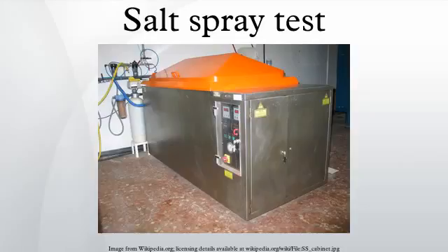The first climate cycle comprises a continuous indirect spray of neutral saltwater or synthetic seawater solution, which falls out onto the specimens at a rate of 1.0 to 2.0 ml per 80 square centimetres per hour. During this spraying, the chamber is dosed with SO2 gas at a rate of 35 cm³ per chamber volume, for 1 hour in every 6 hours of spraying. The entire test cycle is at a constant chamber temperature of +35°C.